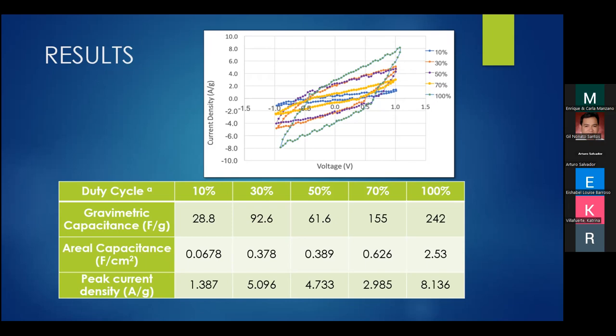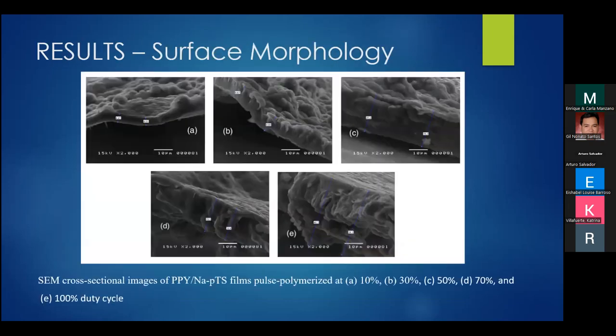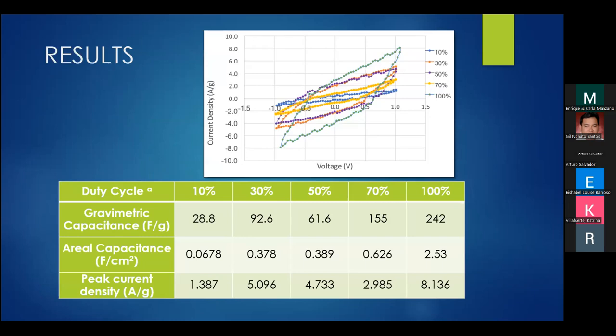So it is correlated, of course, with the porosity of the film electrodes as shown in the SEM micrograph E for 100% duty cycle. Compared to the other films, the one grown at 100% duty cycle is flaky and more porous. So it showed the highest capacitance, because there is better ion diffusion across the material.